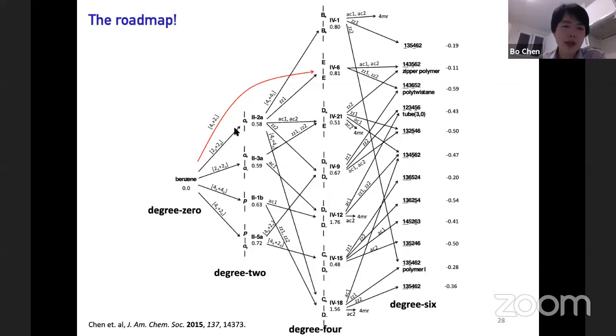So each arrow here represents a topological relationship between the two structures, or a potential reaction pathway between the two structures. We borrowed the notation for the cycloaddition here just to indicate their topological relationships. Usually if you follow an arrow, you increase the degree of saturation by two, so two to four, four to six. But there's one particular two-to-four order cycloaddition pathway that I'll talk about later.